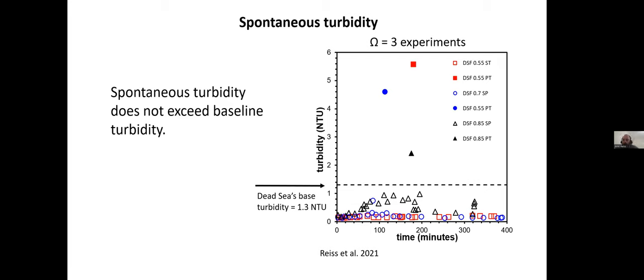We could add experiments also from different ratios of Dead Sea seawater with the same oversaturation, and it's pretty much throughout the mixing ratios in which gypsum precipitates, we see the same thing. So at this oversaturation, we do not expect to see a whitening event.